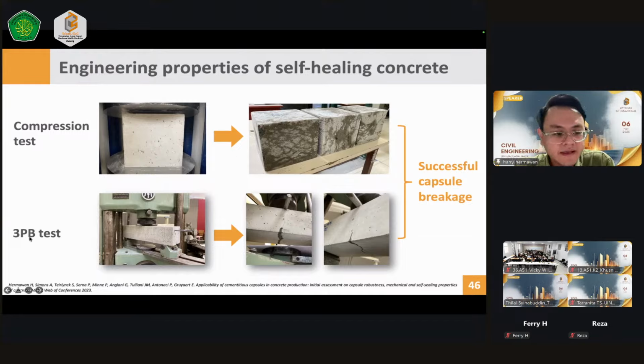This is also the same case with the 3-point bending test, especially on the bottom side. You see also there was a wet area, and it also indicates the capsule broke at the cover zone of my concrete. And both pictures represent a successful capsule breakage.